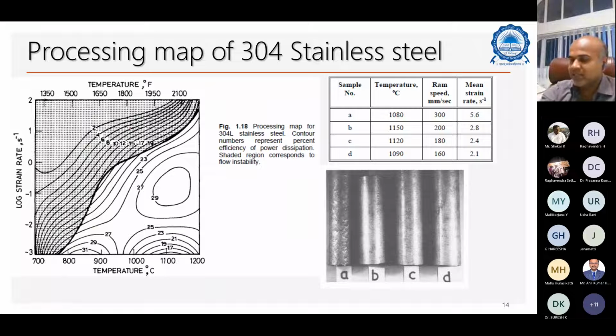so that you will get a desirable microstructure. Similarly, another example, we're talking about 304 stainless steel, right? So this is the processing map for 304 stainless steel, and this is the unstable zone. So you want to avoid this zone, and you want to process in this region. Let's take four different samples A, B, C, D, which correspond to different temperatures and ram speeds. Ram speed is nothing but the strain rate I'm talking about.